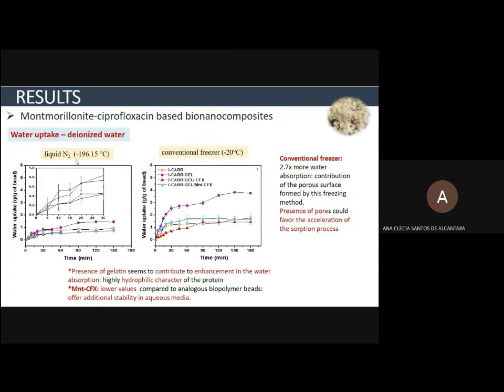Another property evaluated in this study was the water uptake using deionized water. In this case, the water uptake showed different profiles depending on the freezing method employed in the preparation of the bionanocomposite beads. In general, the presence of gelatin seems to contribute to the enhancement of the water absorption, independent of the freezing method used. This enhancement of the water absorption is probably due to the highly hydrophilic character of this protein.